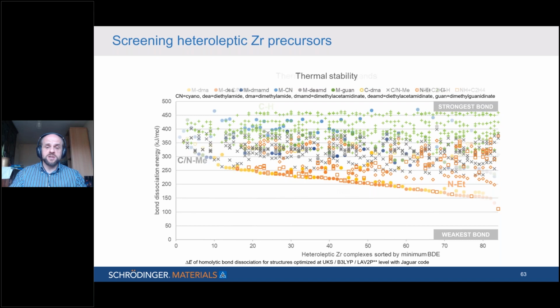So I'll just put everything back together again. I suppose what surprised me most of all by this is the range of the data. You can see it makes a huge difference how the molecule is put together, what the 4 different ligands are. We don't just get 6 sets of bond dissociation energies. It really matters that a ligand is attached to other partners, and that affects its own bond dissociation energy. So we range from 350 kilojoules per mole on the left-hand side down to as low as 100 or 150 kilojoules per mole on the right-hand side, quite a wide spread.